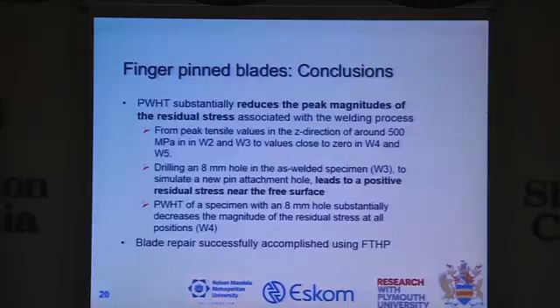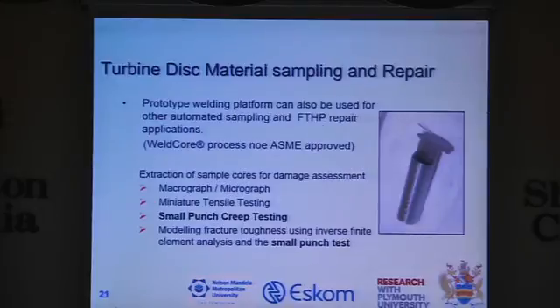Then post-weld treatment of the specimens decreased the magnitude of residual stresses at all positions. Blade repair successfully accomplished.